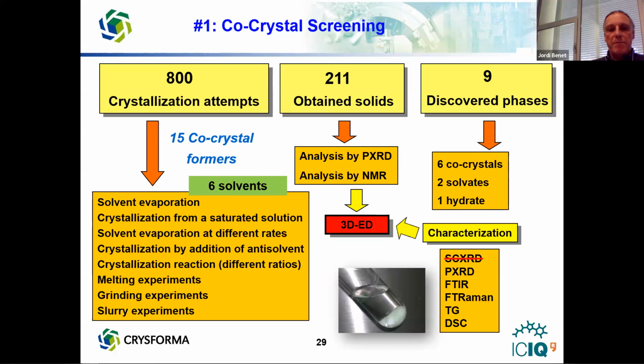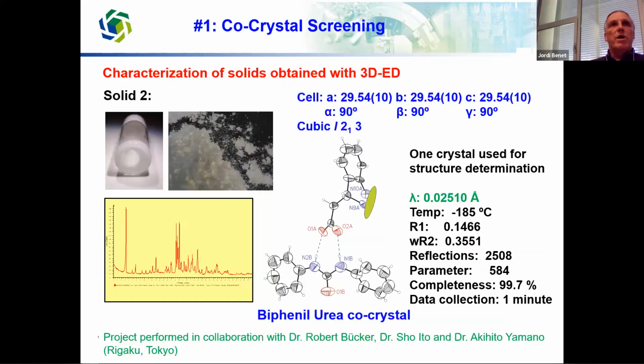So in this screening, for example, what we did is we characterized the first solid. I think it was solid number 2, and just making one measurement with our system. This was because we had high symmetry, so we have a cubic system. We could find out from our API. I cannot show the full molecule, only a fragment, because it's confidential. But you can see that this active pharmaceutical ingredient formed a co-crystal with biphenyl urea. And only with one measurement, which took a minute.